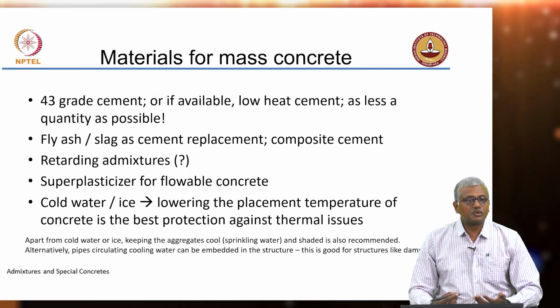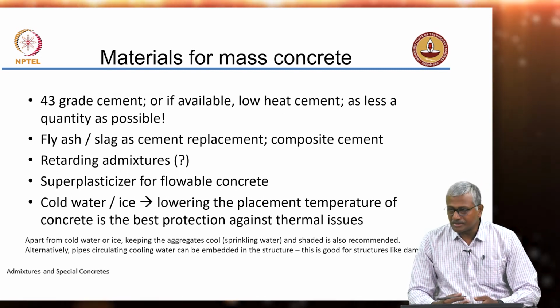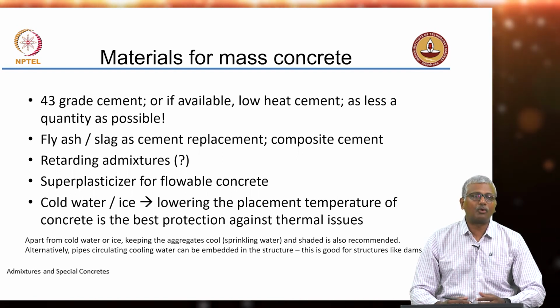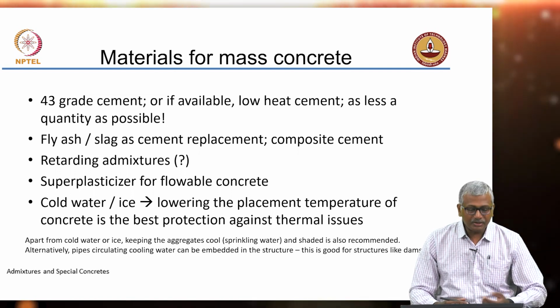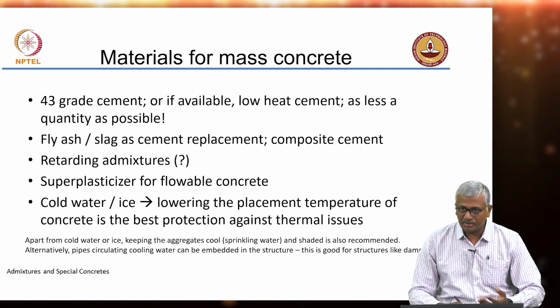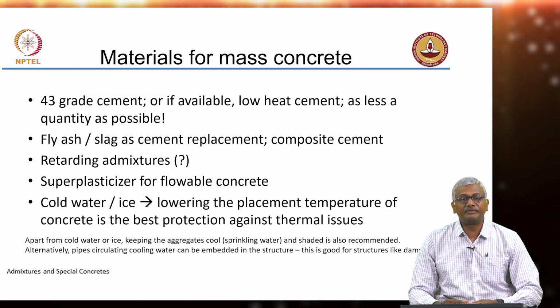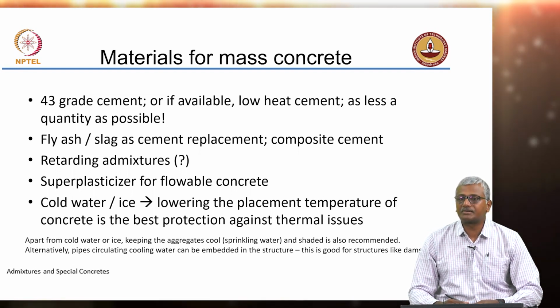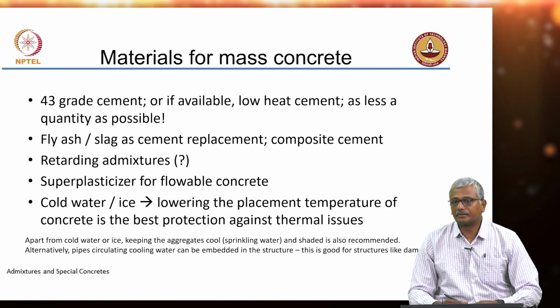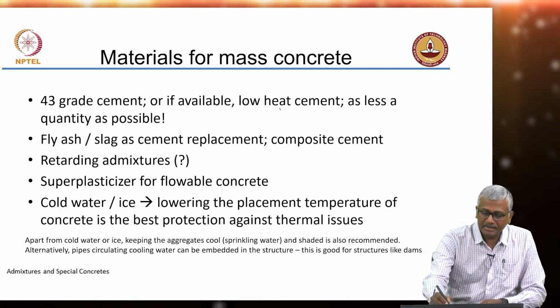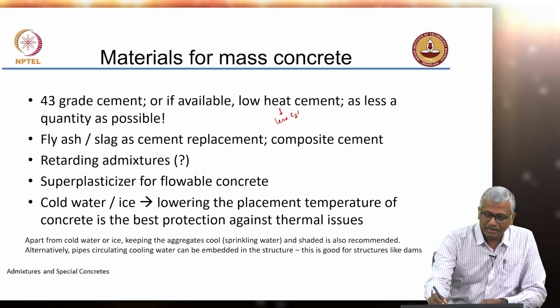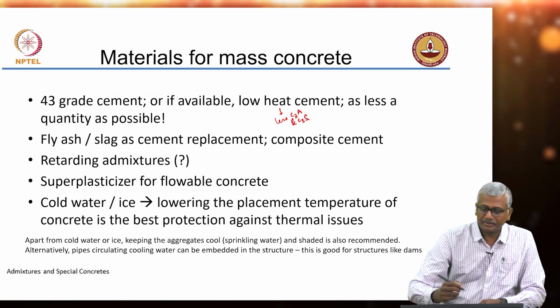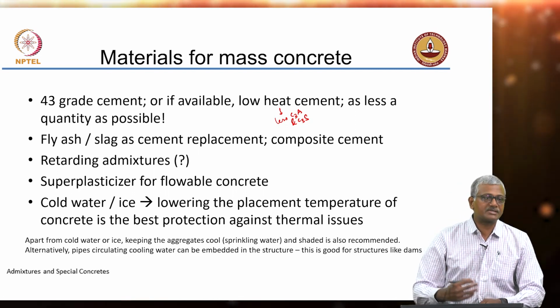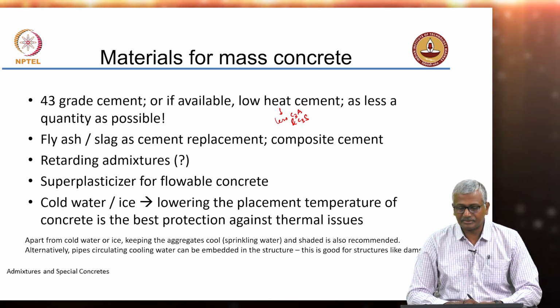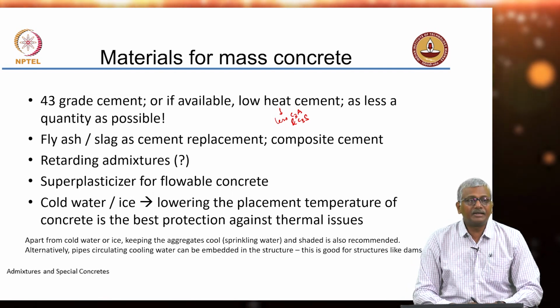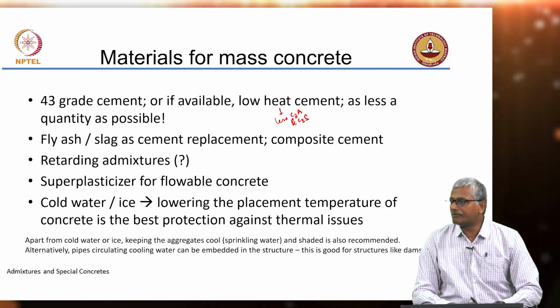So, what kind of materials do we want to use? As I said, heat of hydration is a primary consideration. So, you want to use concrete which will evolve less heat, right, and for that you can choose a cement that is a low grade, that is 43 grade instead of 53, or if available you can choose a low heat cement. What is the characteristic of low heat cement? Yeah, less C3A and C3S. Okay. In the case of low heat cement, you will have more C2S and C4AF and less C3A and C3S.